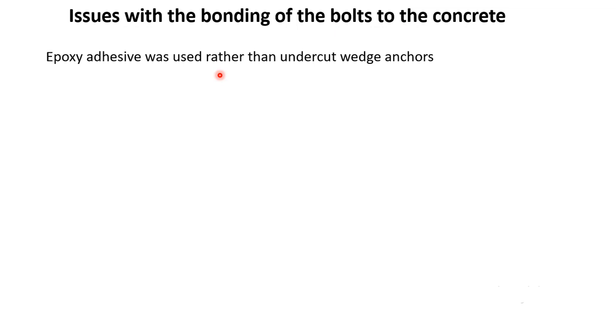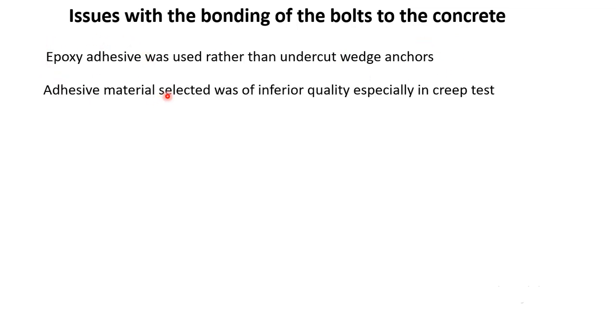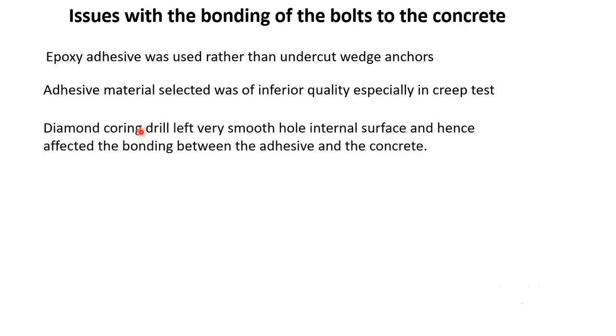So now let us discuss the issues with the bonding of the bolts to the concrete. Epoxy adhesive was used rather than undercut wedge anchors. It was decided that wedge anchors should have been used, but actually epoxy adhesive was used for bonding. Adhesive material selected was of inferior quality, especially in creep tests. So already they had found that the epoxy that was used was of inferior quality, but still they went on and used it. Diamond coring drill left very smooth hole internal surface and hence affected the bonding between the adhesive and the concrete. So as we know, anything that needs to be glued together, the surface should not be very smooth. So it should be prepared, actually the surface is roughened so that you have more surface area for bonding.